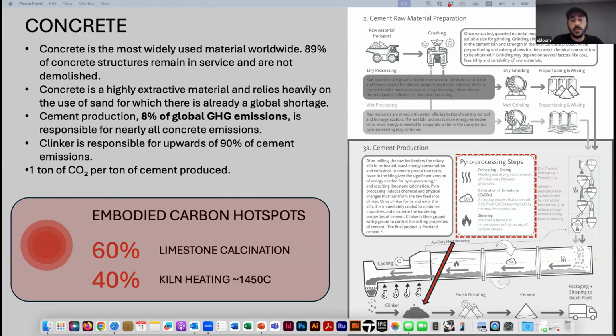And so at the core of the concrete industry's emissions is clinker. Lime is a staple ingredient in ordinary Portland cement. And to get lime, immense heat is needed to heat limestone within the kiln. This is often supplied by fossil fuels. Sorry, the lights are motion activated. There we go. Limestone is heated by fossil fuels. This represents about 40% of cement emissions, but the remaining 60% of emissions stem from limestone calcination, which is a natural chemical reaction where heat drives CO2 from calcium carbonate to leave lime. Next slide.